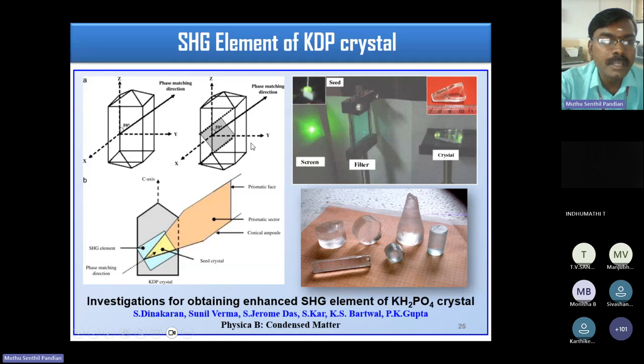So this is the morphology of this KDP, potassium dihydrogen phosphate single crystal. The phase matching direction of this KDP is 59 degrees. So what we have to do is cut the crystal along its phase matching direction using a fine hacksaw blade and frame, mount it at the bottom of the glass sample, and pour the saturated solution inside the glass sample. When we apply the temperature at the top portion of the glass sample, the solvent is evaporated, then the crystal will be grown like this. So this is the green emission produced in the SR grown KDP single crystal, and the same KDP crystal grown in our laboratory, SSN.